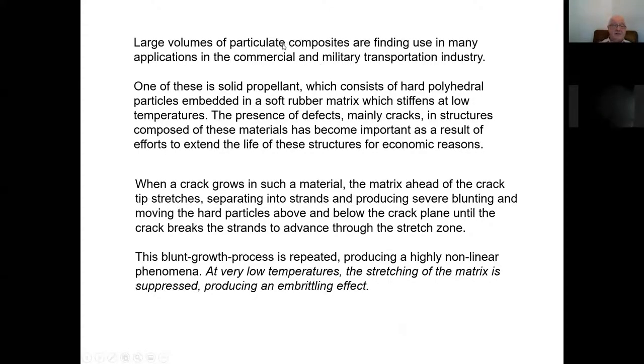Why is this useful? Well, this was applied to a particular problem: solid propellant. Solid propellant is a composite material, a mixture of a soft rubber matrix with embedded particles. The recipe for this solid propellant is available on the internet. But the important thing is that solid propellant is used for different rockets, and it sits at minus 40 degrees. And at minus 40 degrees, the material becomes essentially brittle.